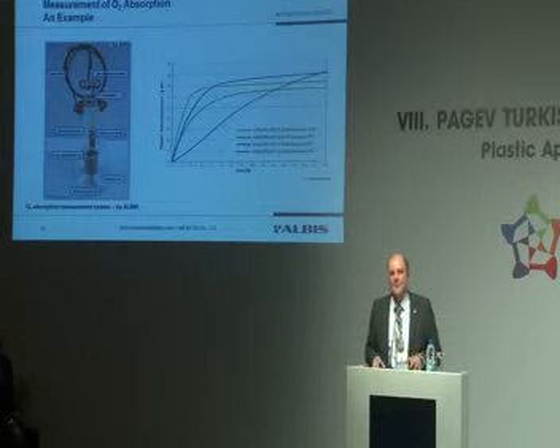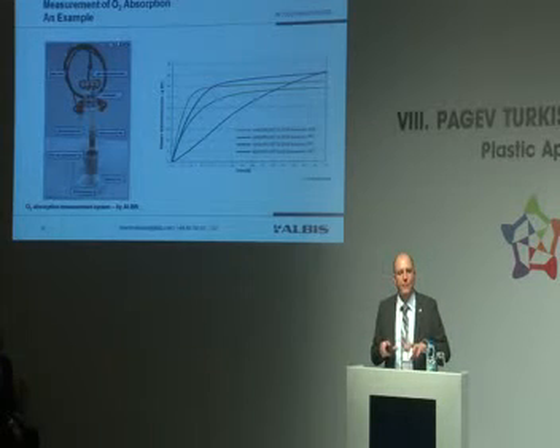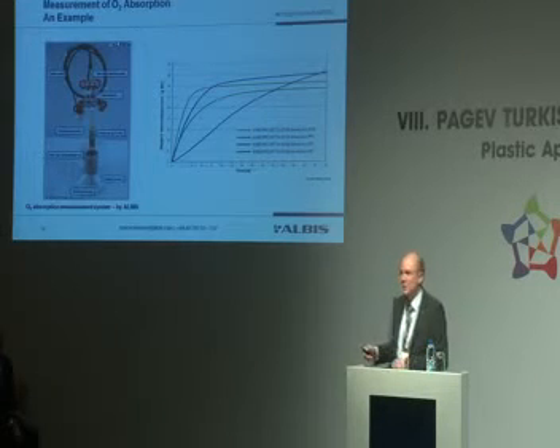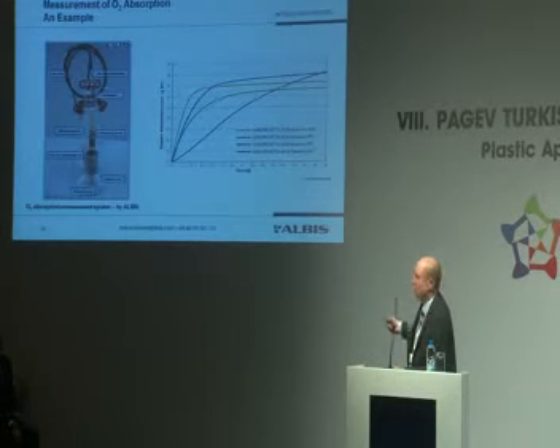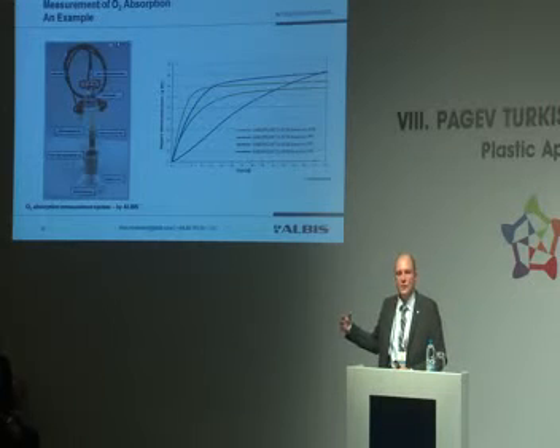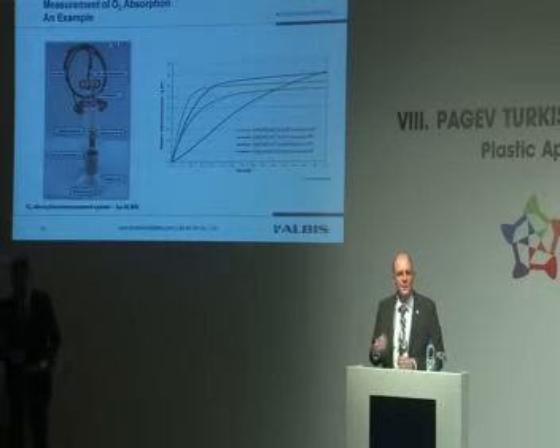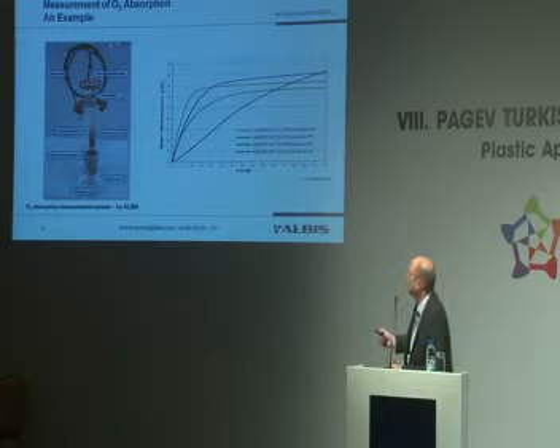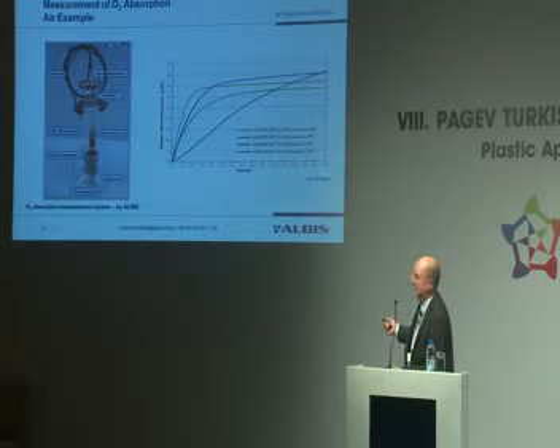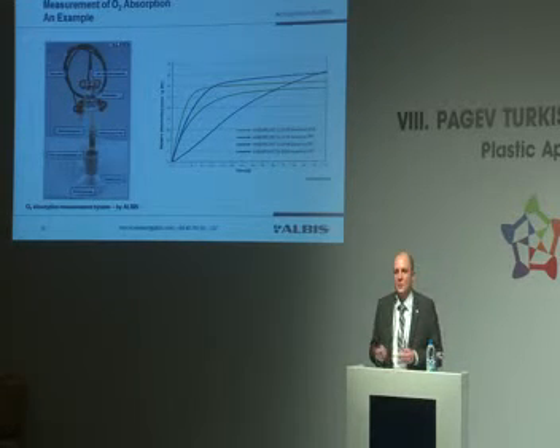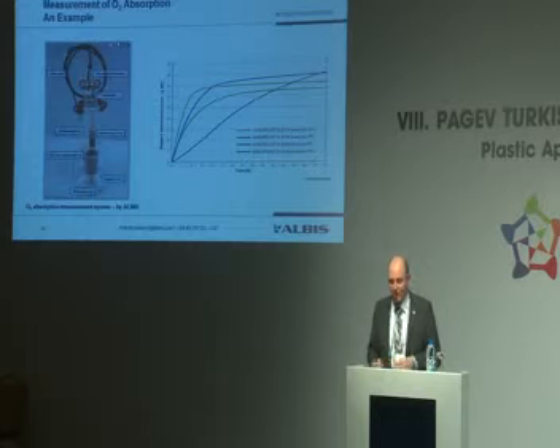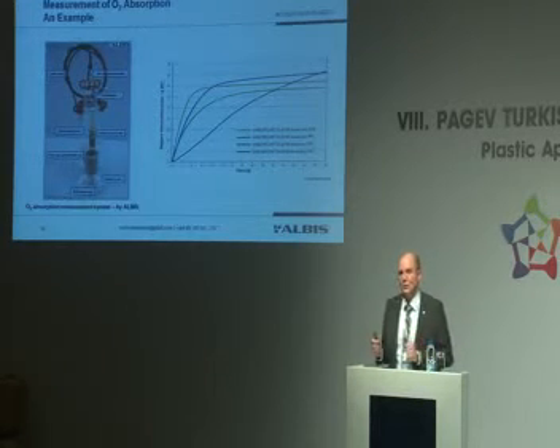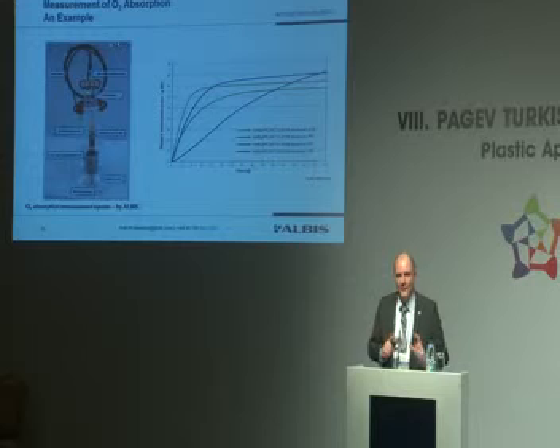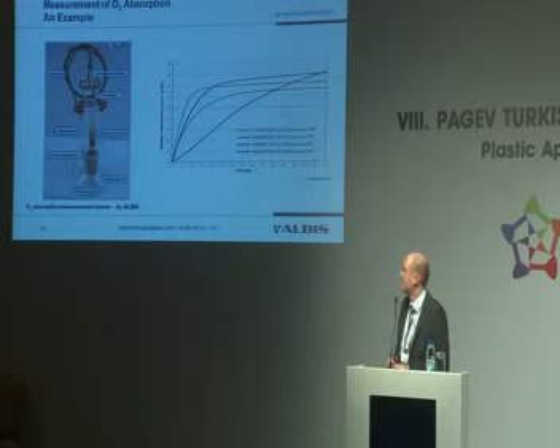And this also explains why we need to combine oxygen scavengers together with barrier materials. Because for these 8 days, the material looks like a barrier. It would not let oxygen through because it catches all the oxygen and transforms it into iron oxide. But after those 8 days, the capacity is full and it opens again. So it would be open to oxygen permeation again. So this is the reason why we always have to combine passive barrier with active barrier materials.